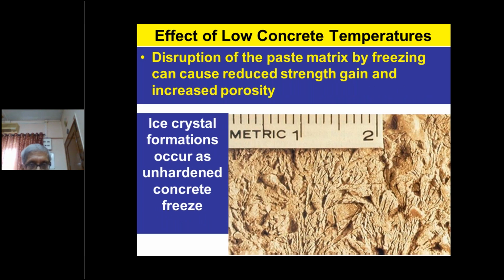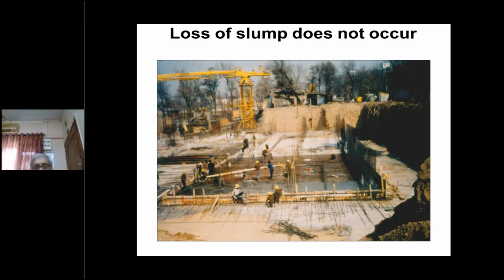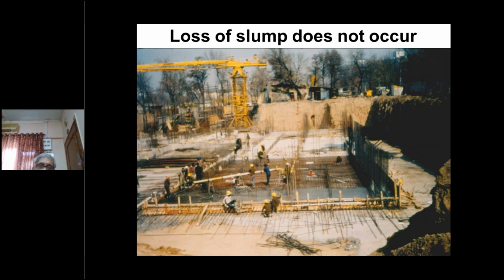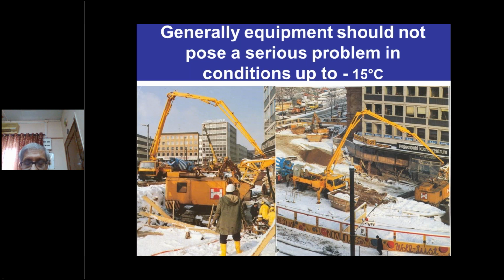And when concrete freezes, you get a design like this. Ice crystal formation occurs as unhardened concrete freezes. So one has to ensure that 3.5 megapascal strength is achieved by the concrete. I will go a little faster. Another advantage we got during the winter was that no slump loss occurs, and therefore we could do longer stretches of pipeline. We went to a maximum of 300 meters. Of course, now the world record is more than a few kilometers, and concrete was pumped beautifully without any problem. Generally, equipment should not pose a serious problem in conditions up to minus 15 degrees Celsius, because the electronic fuses and the hydraulic oil do not freeze up to minus 15 degrees centigrade.